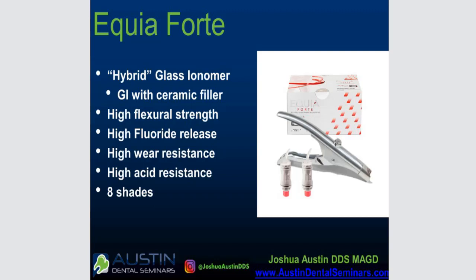The difference that separates this from a Fuji 9 or one of those really early pure GIs that we would have used in dental school is that this has a very nice ceramic filler in it that gives it a much higher flexural strength and much higher wear resistance than a Fuji 9 or a more traditional, pure glass ionomer. Also a higher acid resistance. We do have 8 shades in this, which is pretty high for glass ionomer. Typically speaking, there's not that many shade choices, but you do get a decent amount of shade choices here.